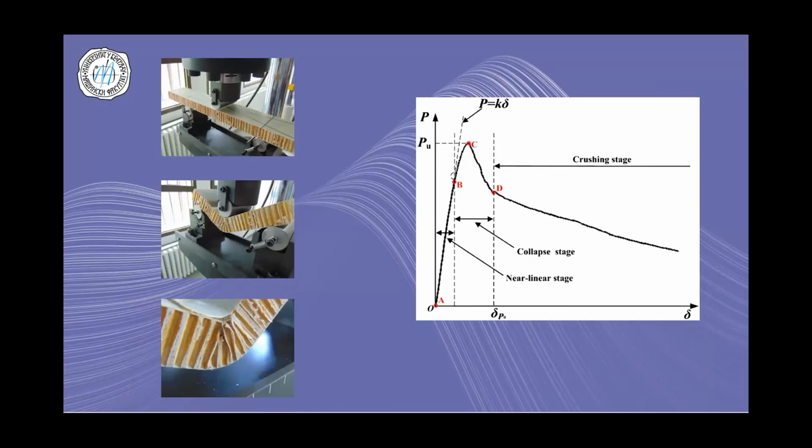So, just to illustrate this approach, this is our initial test that we've done, where we actually recognized the totally non-linear behavior of our plates. And these models that were initially suggested in the literature are actually valid only in a small, initial range, let's say up to point B. After that, nonlinearity occurs, and collapse occurs, crushing occurs, and so forth. What I'm trying to say is that these equivalent models are only good for a small part of the region, the initial region.